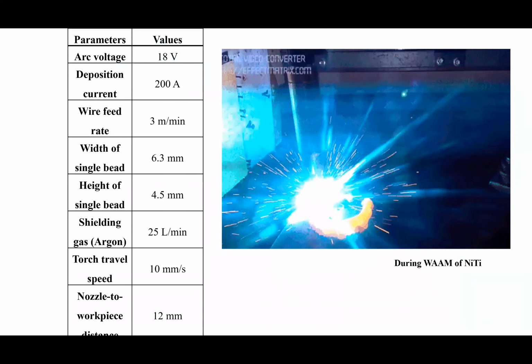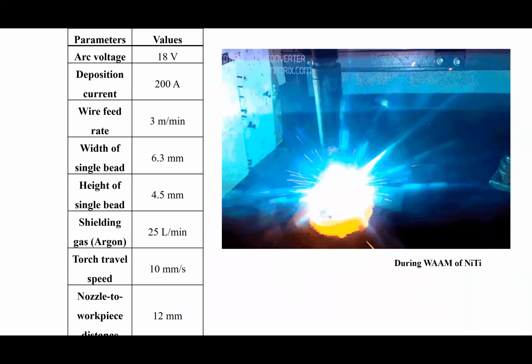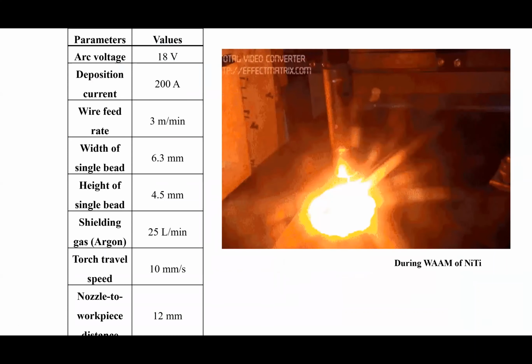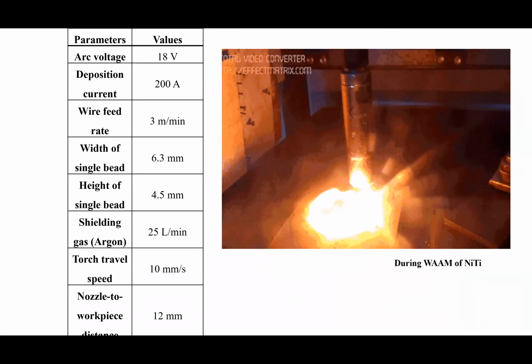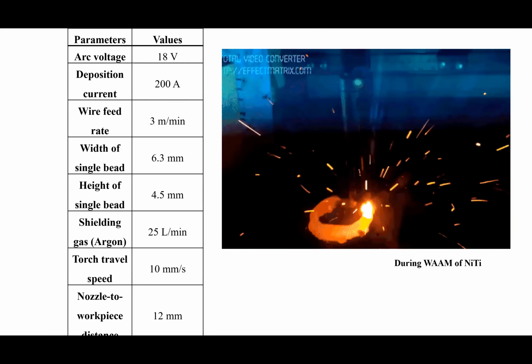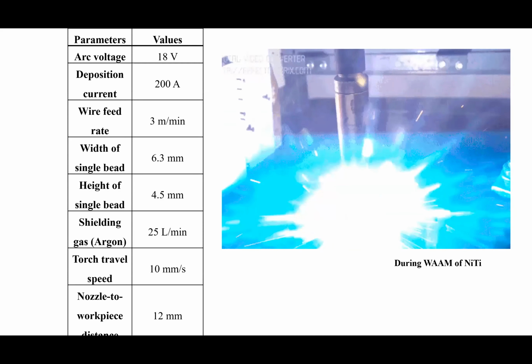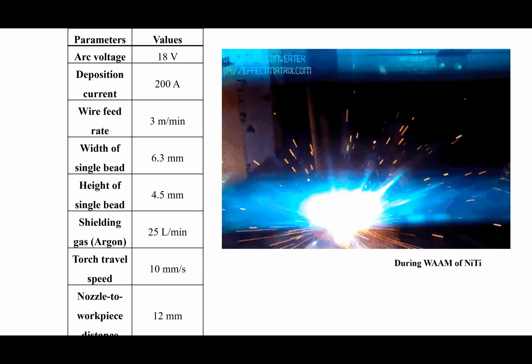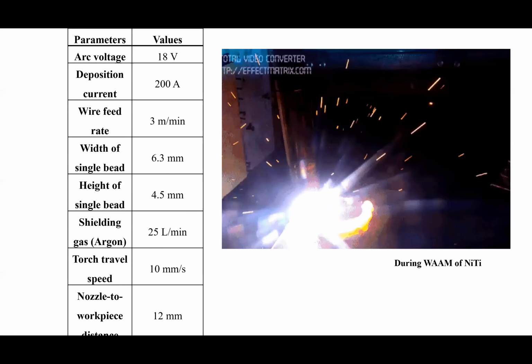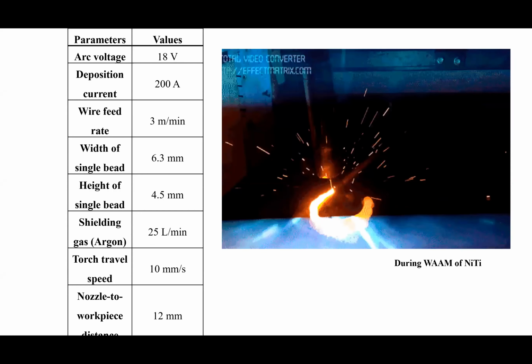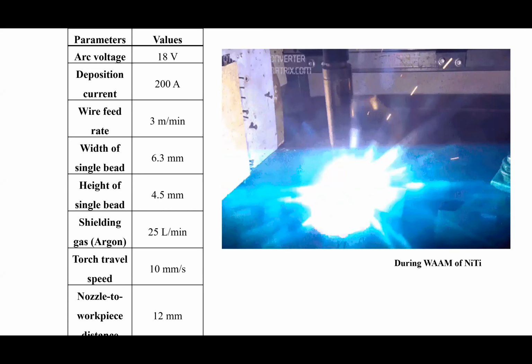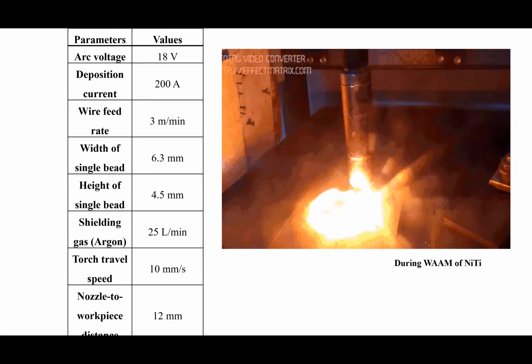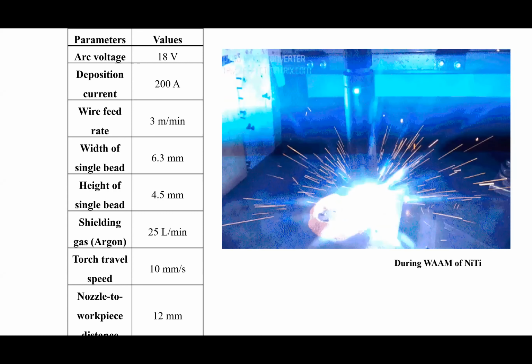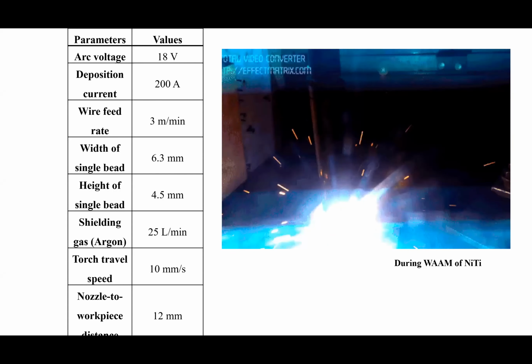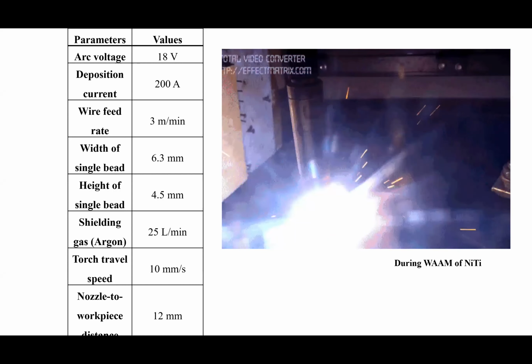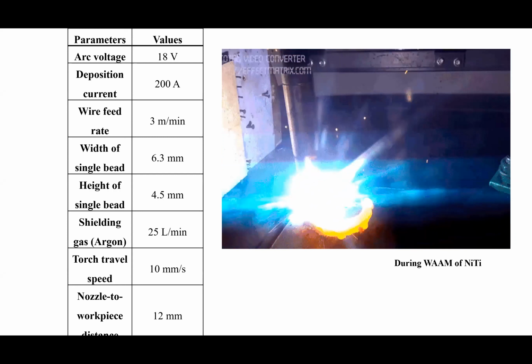Okay, so as far as this wire arc based system is concerned, we could manipulate two different heating bed systems. One heating bed system has the capability to vary the temperature from room temperature to 650 degrees Celsius, so that we can take care of the crystallization during the building of the structures. Another is that the bed had a cooling arrangement where we can pump liquid nitrogen inside it, so that we can take care of the crystallization behavior in that structure. So we had a kind of turret mechanism so that we can fix into these structures.